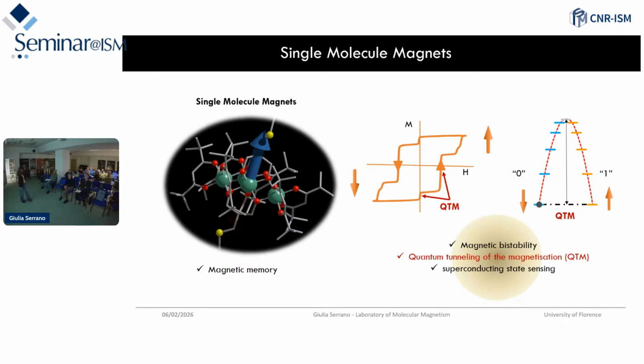And the combination of these two factors creates, at very low temperature (very low depending on the kind of molecule), an energy barrier that hinders the reversal of the magnetization. So our bit 0 and 1. So at low temperature, the magnetization of the single molecule magnet is blocked, and then we can observe a hysteresis loop associated to the single molecule or to a molecular layer that we have on the surface.